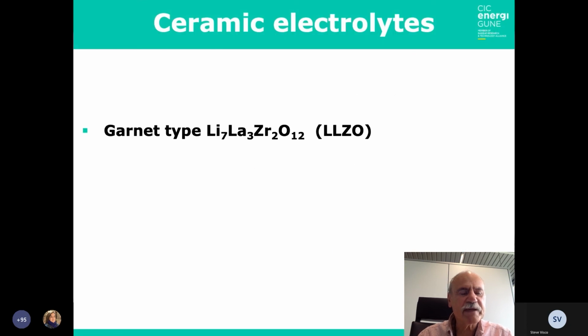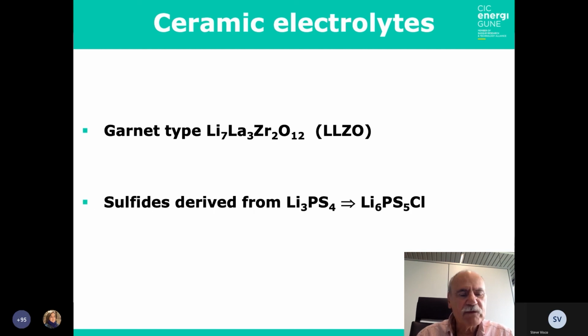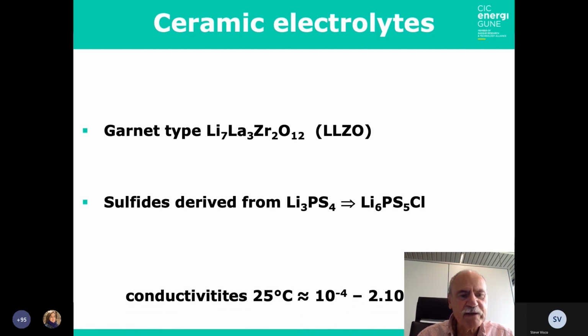Ceramic electrolyte can be garnet type, like the LLZO, which is zirconium, lanthanum, lithium oxide. And you have sulfide derived from Li3PS4, which is Li6PS5Cl, like argyrodite. And the conductivity at room temperature of this electrolyte is quite high, between 10 to minus 4 and 10 to minus 3, possibly reaching 10 to minus 2 at room temperature, as I say.